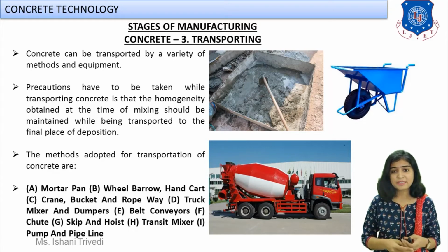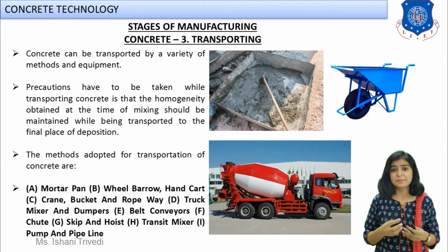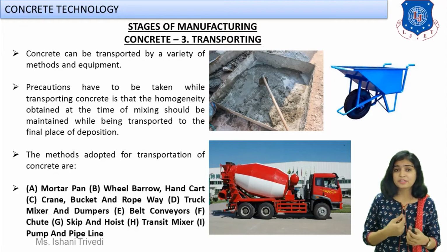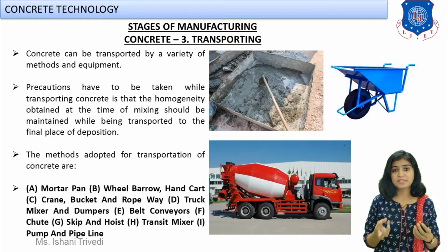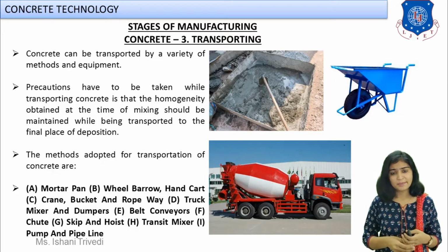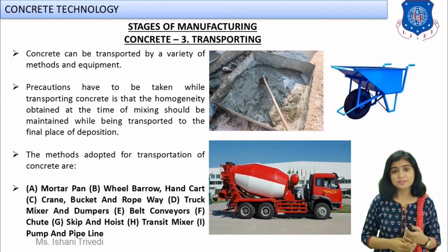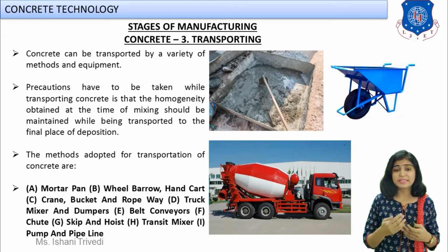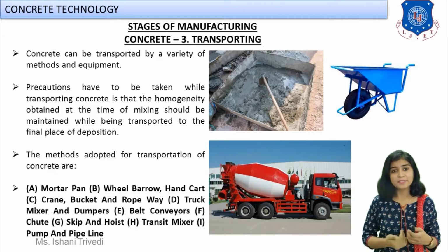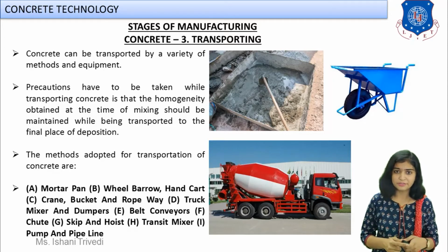But great care should be taken when you are transporting the concrete. There should be no segregation or bleeding in the concrete work. It means the separating out of the ingredients. When the concrete mix takes lots of turns in the pipelines and belt conveyors, it can happen that the materials get segregated. It should not happen. Also, there is a time limit for transporting concrete. Premature hardening should not take place when you are transporting it. So on time it has to be delivered and placed. Within a 90 minute gap at the most, this mixing, transporting and placing work has to be done.